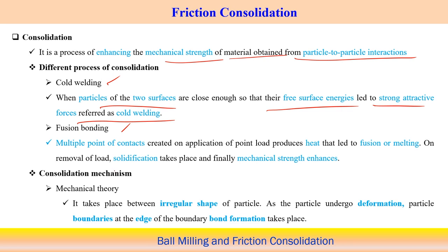So in this case, multiple points of contact are there with the application of the load, which tries to reach the melting point at this very localized position. That localized position tries to bond together in the form of a fusion bonding, which usually happens at this particular point. Now on removal of the load, solidification takes place, and then the mechanical strength enhances.